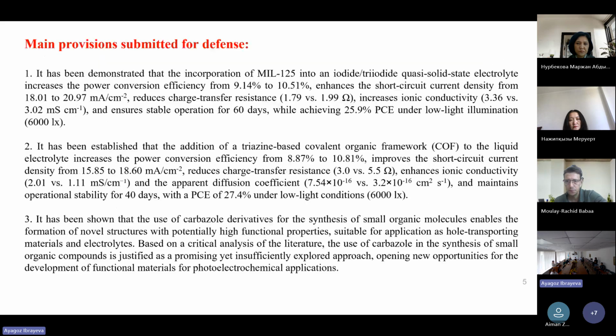And the main provisions are made for the defense. It has been demonstrated that incorporation of MIL-125 electrolyte enhances the power conversion efficiency from 9.14 to 10.51. Also it increased the short circuit current density from 18 to 20. And by the electrochemical properties, it reduced charge transfer resistance from 1.99 to 1.79, and increased ionic conductivity from 3.02 to 3.36. Also, it has good stability for 60 days and works very well under dimmed light.